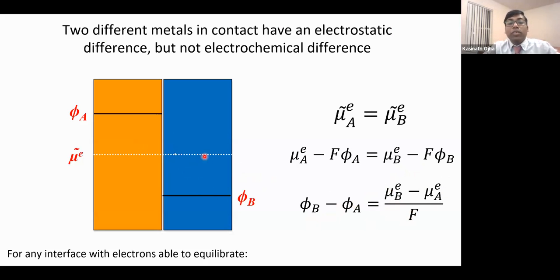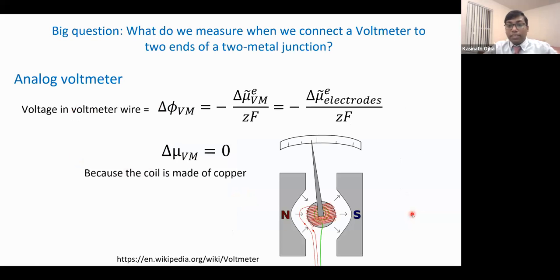So that means, if we connect a voltmeter to both sides of these two metals, then what are we going to measure? We're going to measure the chemical potential difference between the two metal phases. But in reality, we generally measure 0 volts. Nothing happens. That's because we should actually measure an electrochemical potential difference, but that is 0 because in the voltmeter, both sides of the wire are made of the same material. Let's say it's copper, so it's the same material.